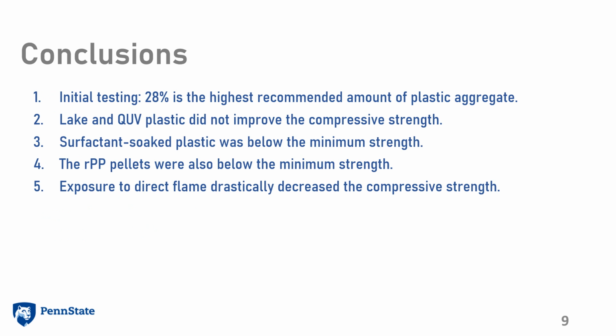In conclusion, it was determined from initial testing that 28% plastic aggregate replacing the sand by volume percent is the highest recommended amount of plastic to incorporate into concrete and still maintain compressive strength values required in the ASTM standard. The environmental effects of lake and QUV plastic did not improve the interfacial adhesion and compressive strength of the concrete. Surfactant soaked plastic was below the minimum strength due to it likely hindering the cement curing. The recycled polypropylene pellets were also below the minimum because the spherical shape does not deflect a crack tip effectively. It was also determined that exposure to the flame for 5 minutes decreased the average compressive strength by 30%.